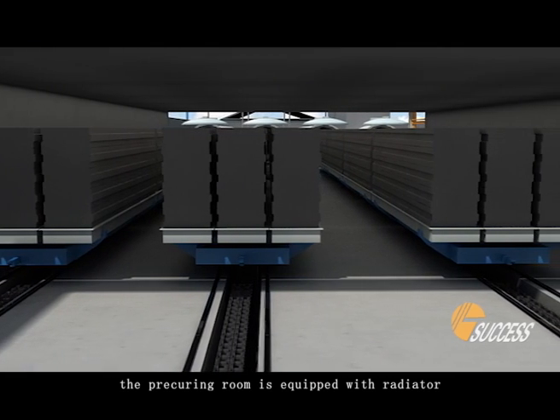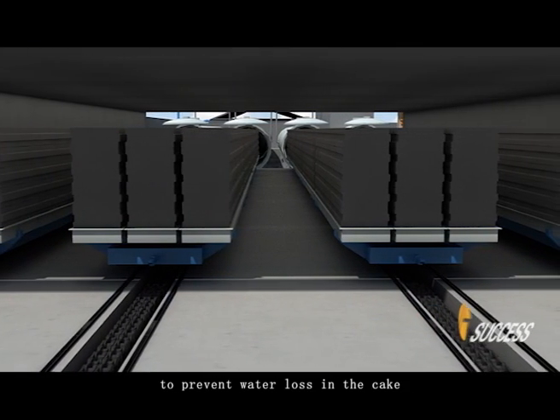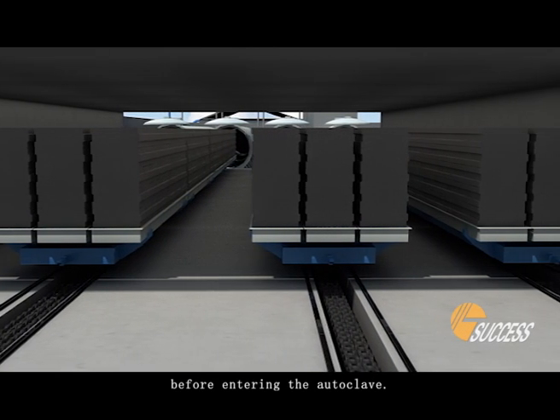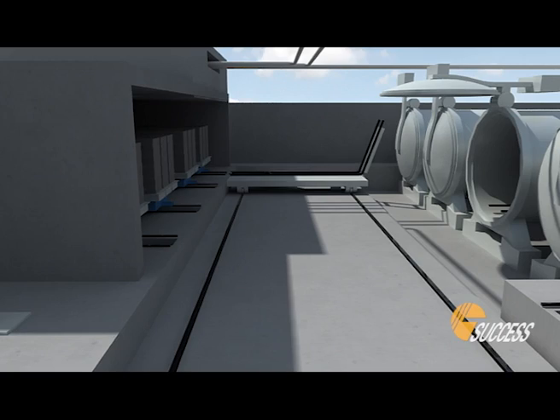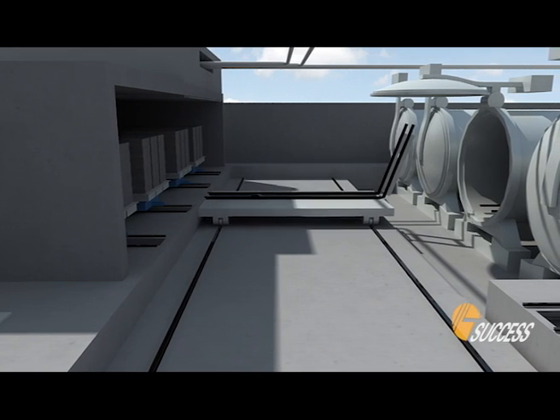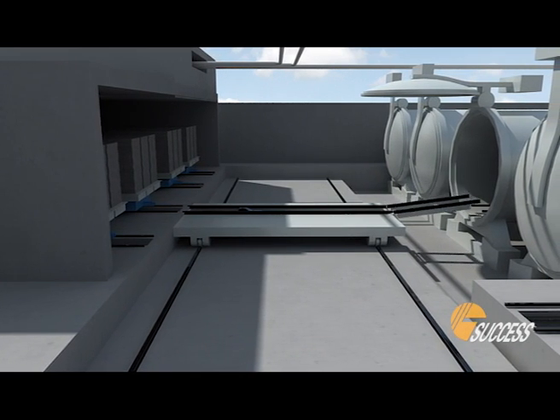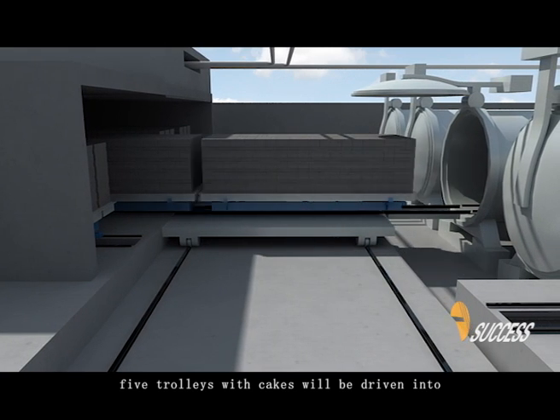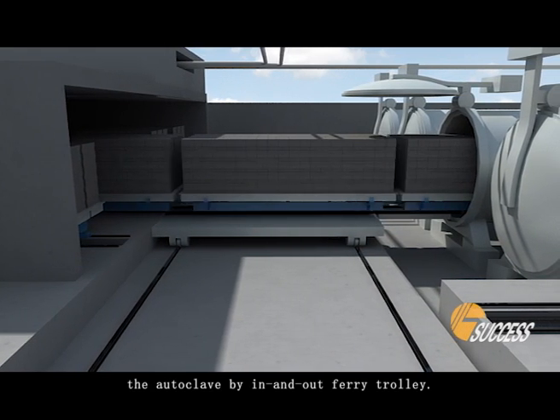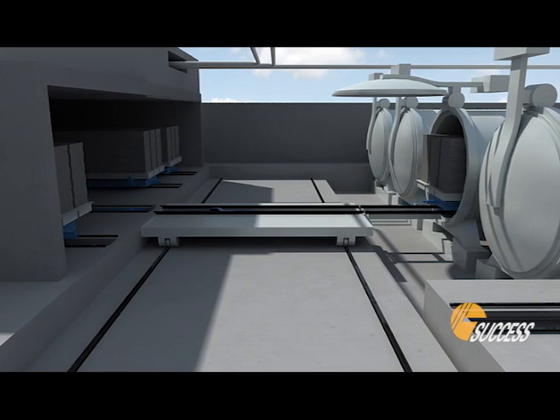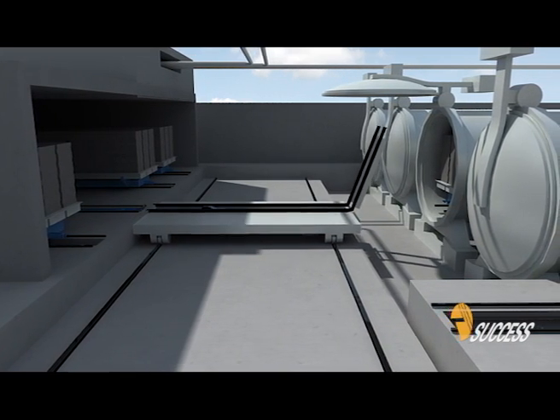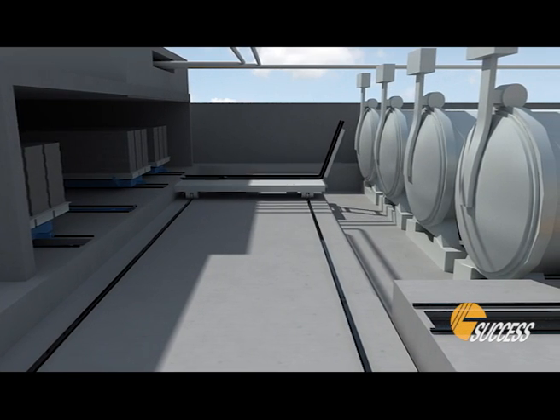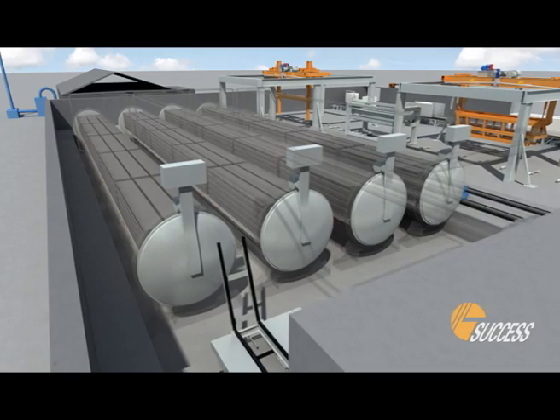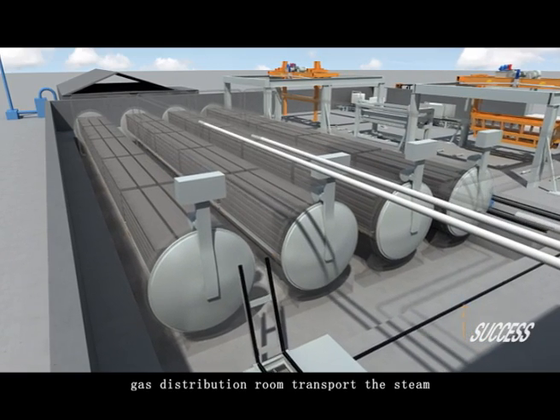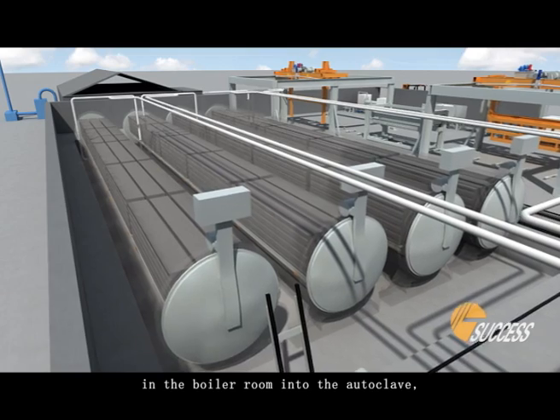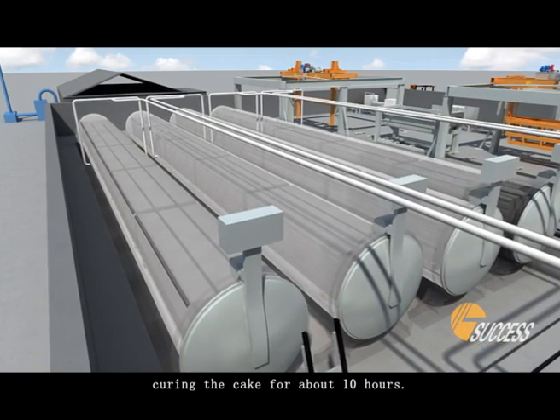The pre-curing room is equipped with radiator to prevent water loss in the cake before entering the autoclave. Five trolleys with cakes will be driven into the autoclave by in-and-out ferry trolley. Gas distribution room transports the steam in the boiler room into the autoclave, curing the cake for about 10 hours.